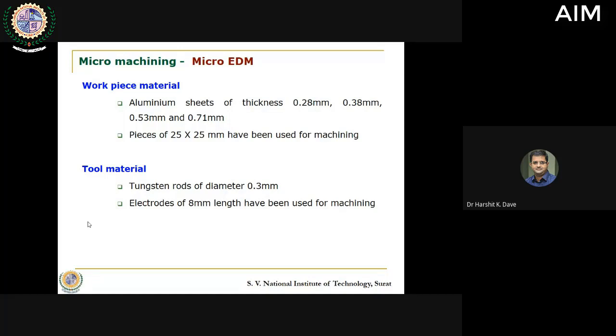We used tungsten rods as our tool material. The supplier of the machine has provided tungsten rods of 0.3 mm diameter. This diameter is 0.3 mm, 300 microns, but the length is 12 inches. Now what we might think is because this is 0.3 mm, we can easily break this. Or you can think that we may use a mechanical hacksaw and cut it. That is also a possibility. Now that was a very tedious task. We wanted to cut electrodes from this with a length of 8 mm and 0.3 mm diameter. That is what we wanted to do.